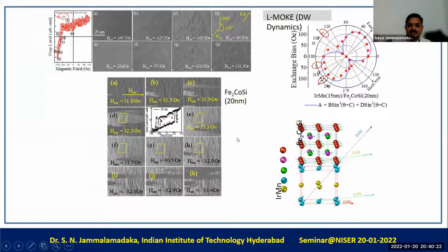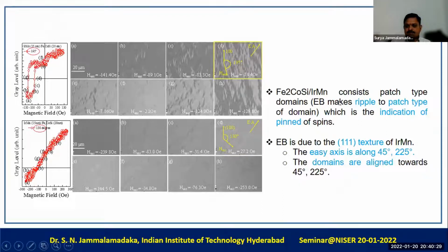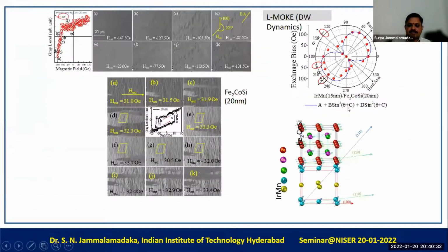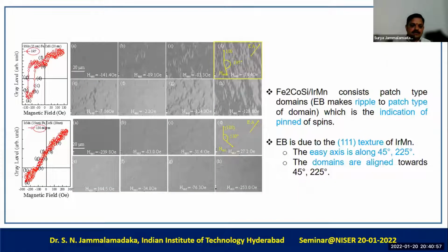45 degrees angle. And if you see the Fe2CoSi single layer, we do see a ripple kind of domains in the single layer. However, as soon as we deposit Fe2CoSi on top of the iridium manganese layer, we do see patch kind of domains. Basically, patch kind of domains come into the picture when there is an interfacial pinning, which leads to the patch kind of domains in our present system.